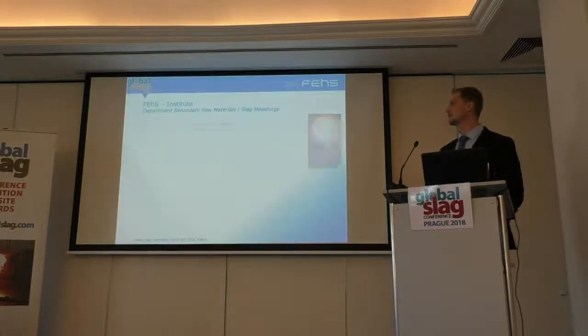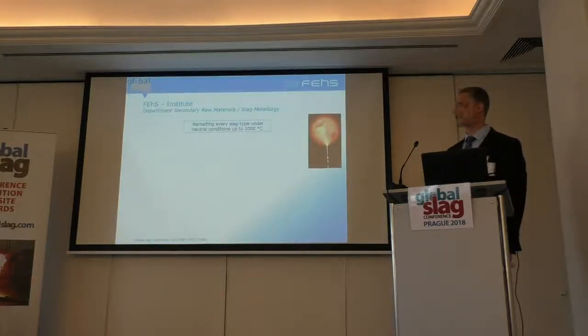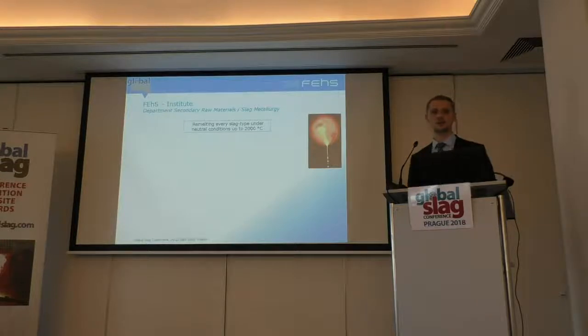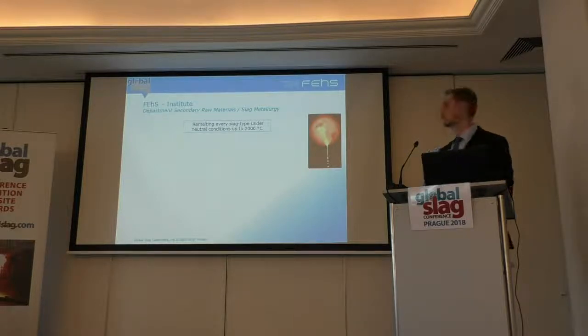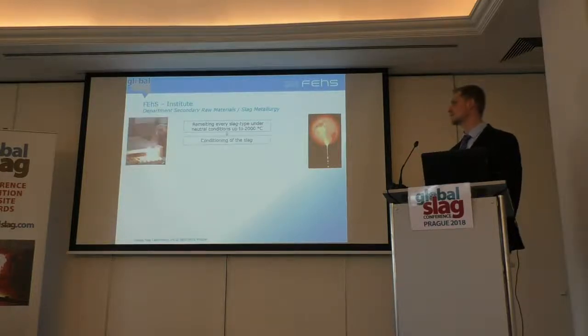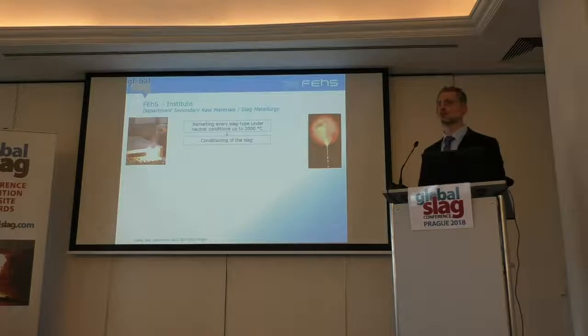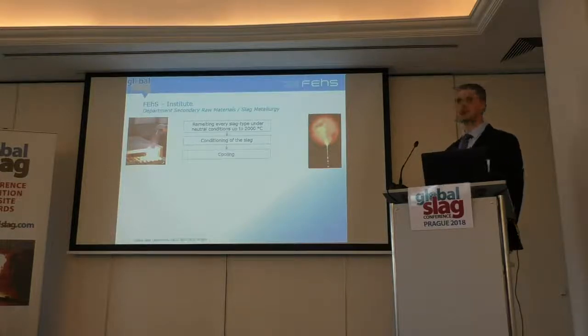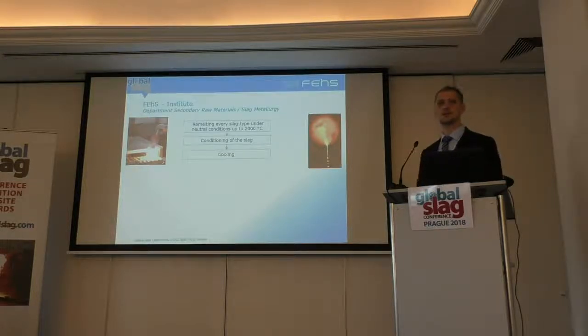So first of all, I would start with one slide where I show you what we are able to do in the melting labs. That is where we did all the melting tests I will show you today. So in our melting lab we are able to remelt every slag type under neutral conditions up to 2000 degrees. We can make a conditioning of the slag, a chemical treatment, and we have different possibilities of cooling.